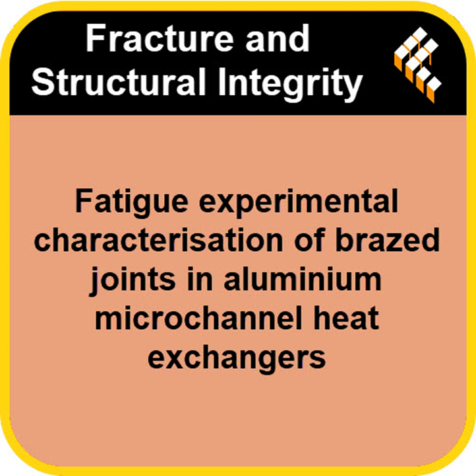Absolutely, perfectly. The physical evidence was entirely consistent. Crack initiation was consistently found exactly where the simulation predicted, right at the brazed joint toe, along that lateral edge of the MPE tube. And critically? And critically, yes. This location also matches where service failures have been observed in actual heat exchangers out in the field. So the lab work directly correlates with real-world experience. Okay. And when they zoomed right in on those fracture surfaces, what did they see? Were there typical signs of fatigue failure?